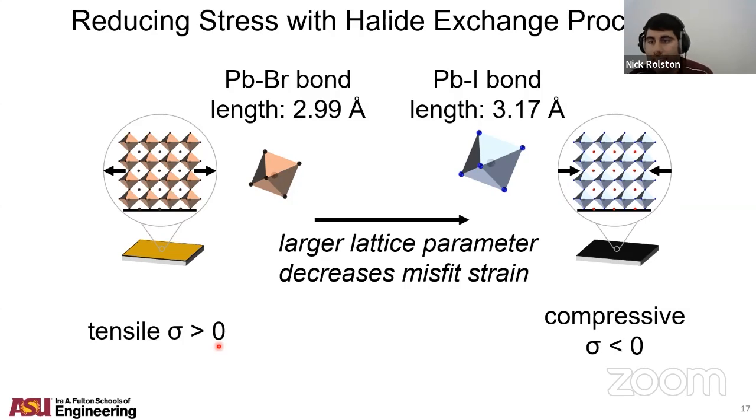It was mentioned in the discussions earlier that we could get up to even the gigapascal range, depending on what substitutions are used. In this case, for this type of transition, we would expect something on the order of 100 or so megapascals, so a little bit less, but still enough to overcome any residual tensile stress. And so our initial trial at this was to take basically an